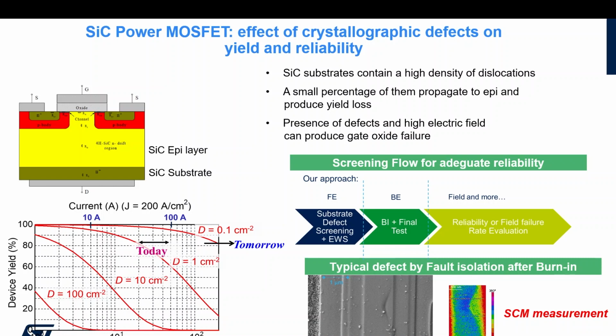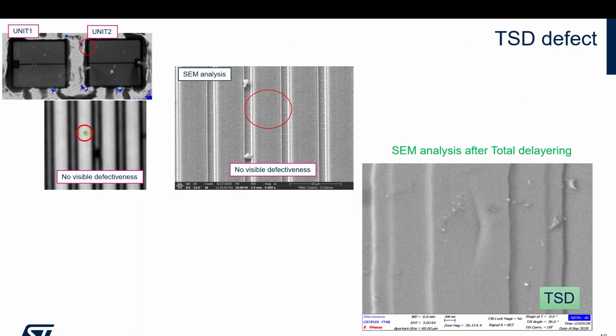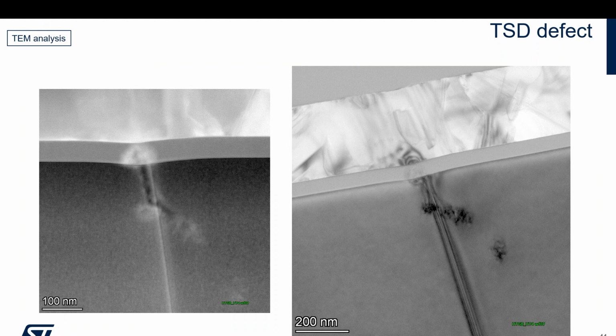So along the line, we've done a lot of study and understanding of, for example, defects that do not show in the yield, like what is called threading screw dislocation, which has to be taken seriously into account. That's how it appears in your device. It is a dislocation coming from the substrate, reaching the interface between silicon carbide and gate oxide, and producing electric field crowding here, which can then be responsible for oxide failure during the application. So you have to eliminate these defects from the final product.